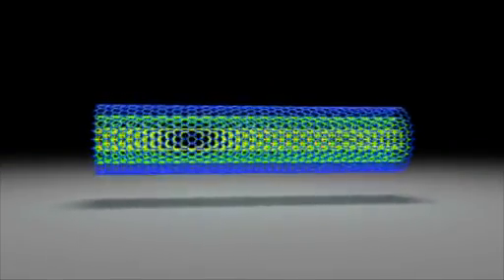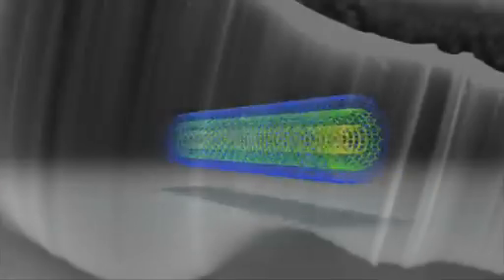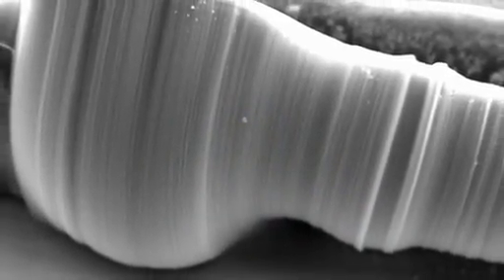The Goddard samples were grown multi-walled, so they're not just single-walled nanotubes. They're also oriented straight up and down. The reason that the oriented samples are darker is because they're low density — light can go in, it gets rattled around in there, and it gets absorbed.